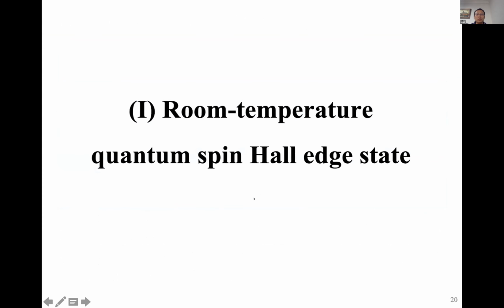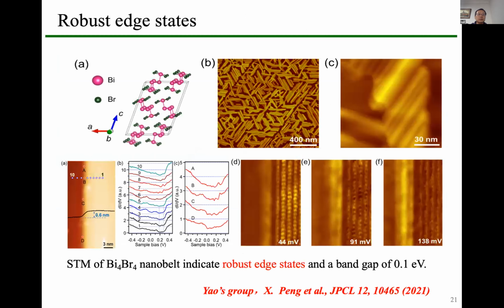So the technique we use is STM. We first grow bismuth bromide on a tantalum selenide substrate. We can obtain this kind of nanowire structure. This tilted surface is the 001 surface. On this surface, we can find some single layer step edge.